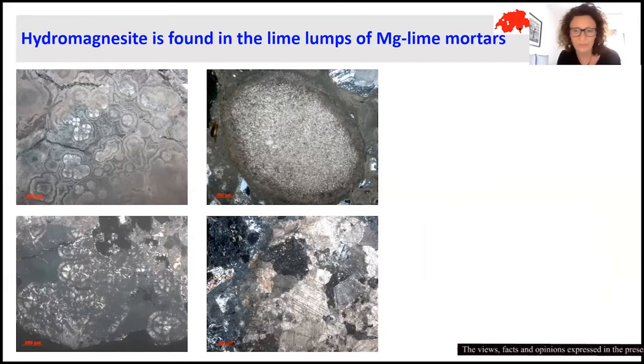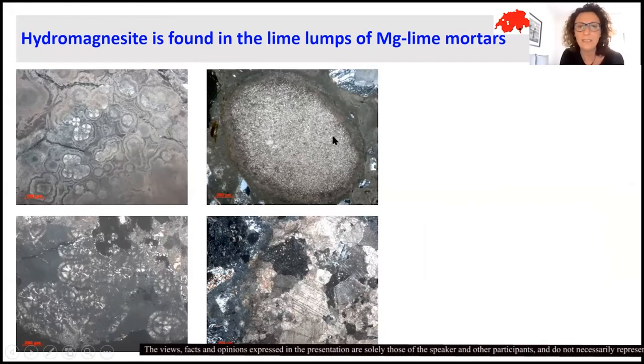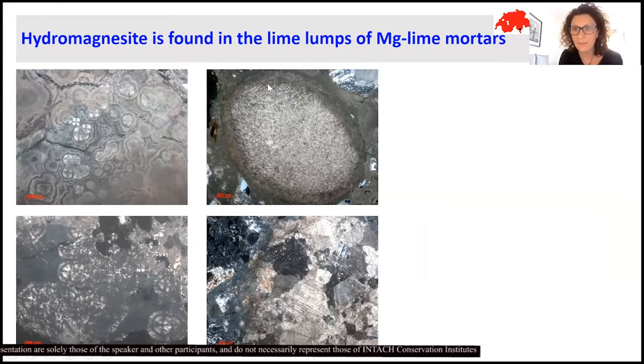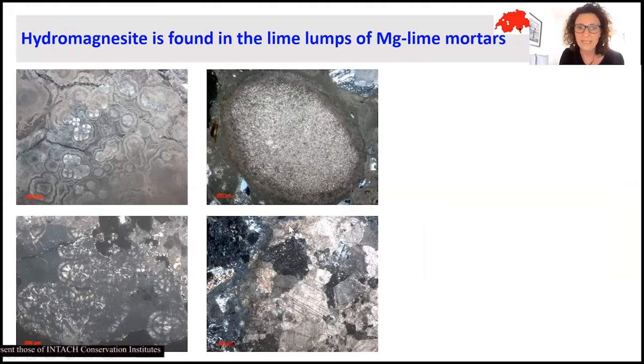If we are not so lucky to find these hydromagnesite components, we can also observe the underburned lime lumps and see if there is the presence of dolostone, as in these two cases I show you. And this is another indicator of the use of a magnesium binder. The problem of the optical microscope itself is that I can only resolve crystals with a dimension not bigger than 30 microns, which is the thickness of a thin section. So all the minerals of a lower dimension cannot be resolved by the optical microscope.